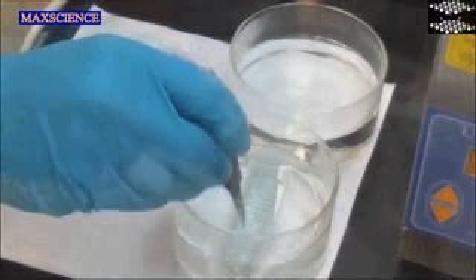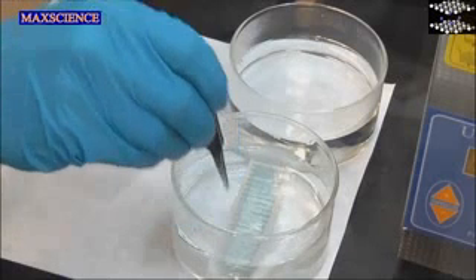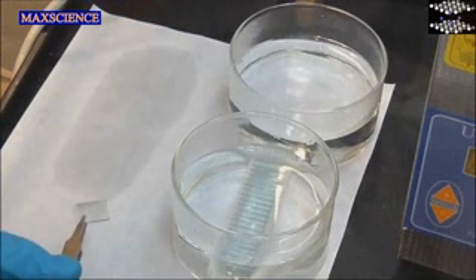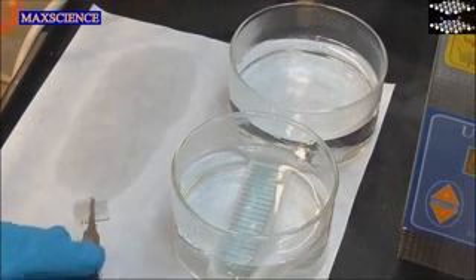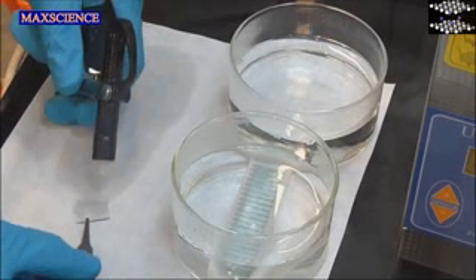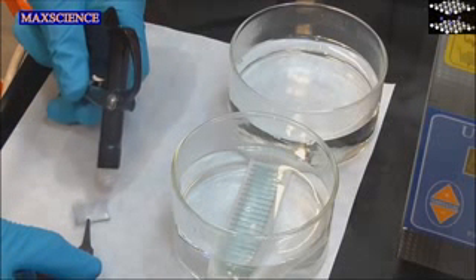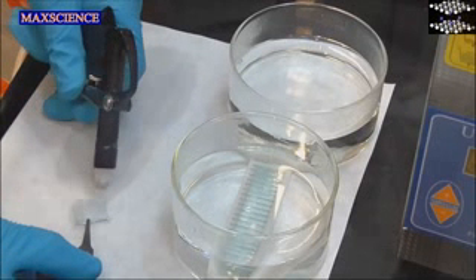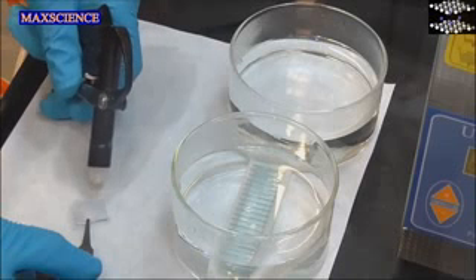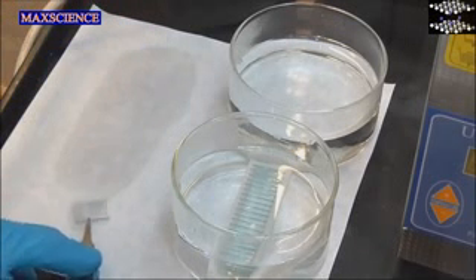Remove the substrates one by one from the holder and place them ITO side upwards on a clean room tissue. Hold the substrates with a pair of tweezers, being careful not to scratch the ITO. Use compressed nitrogen to blow away all the water. Carefully lift the substrates and place them on a hot plate, heated to approximately 120 degrees Celsius.